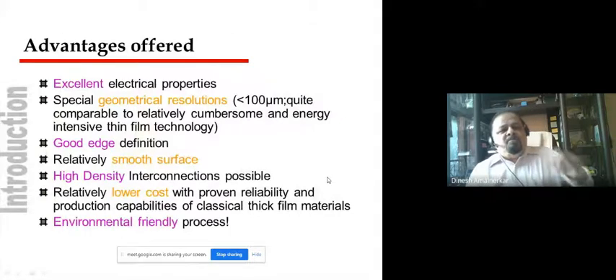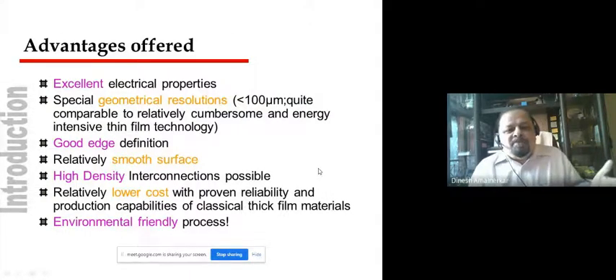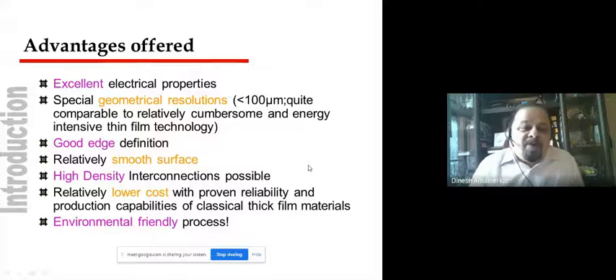Now, why do we need photo patterning, either photo imaging or photo defining? Because they can lead to excellent electrical properties. Most importantly, spatial geometrical resolution of less than 100 micron is possible. By traditional thick film technology, you can't get this kind of line and space resolution. That's because of a limitation of the technique itself. Maximum you can get is 150 micron. Less than 150 micron is literally impossible by classical thick film technology. That is why we wanted to switch over to this particular technology.